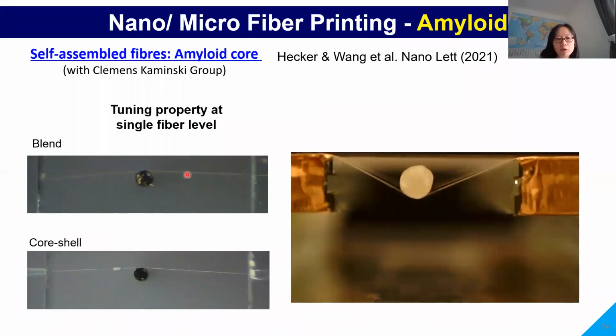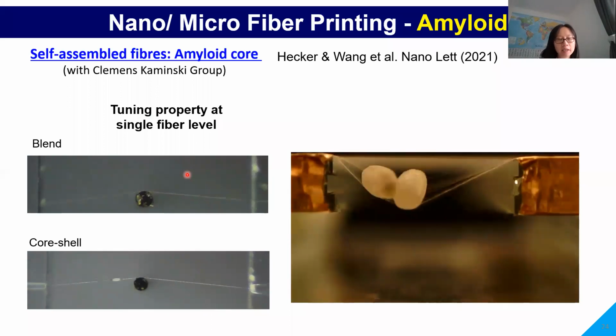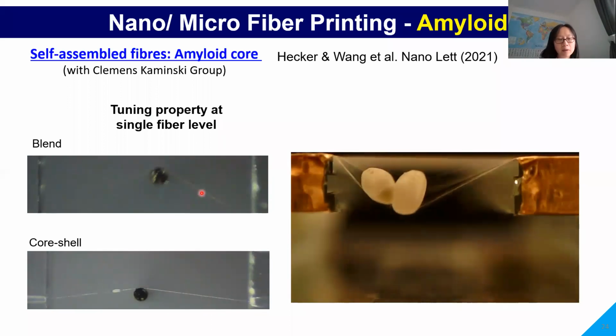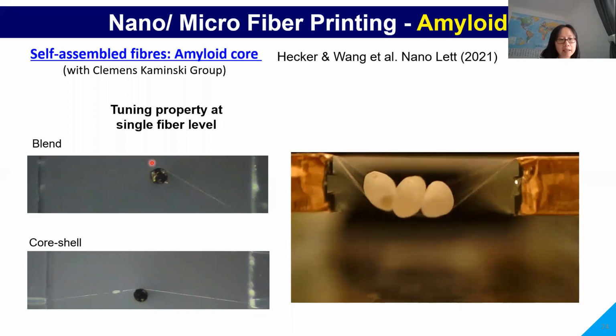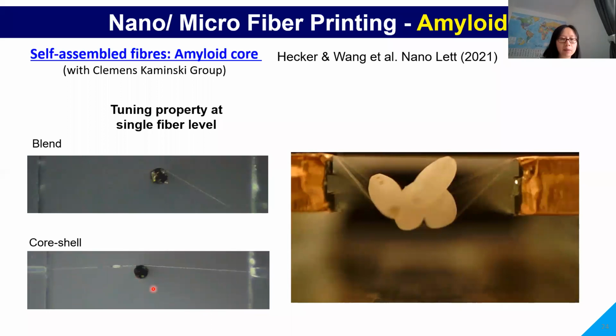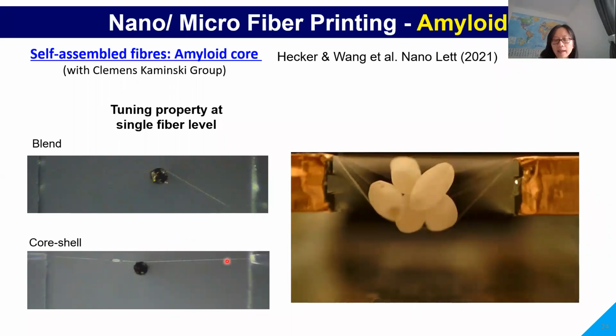With a core shell flow, we can start to tune the mechanical properties of the fiber at a single fiber level. In a blended state, as you can see here, the fiber is very brittle, but in the core shell state, the fiber is elastic and also could be ductile. And with this, we can start bringing nanoscale self-assembly up to centimeter scale long fibers with bulk performance.